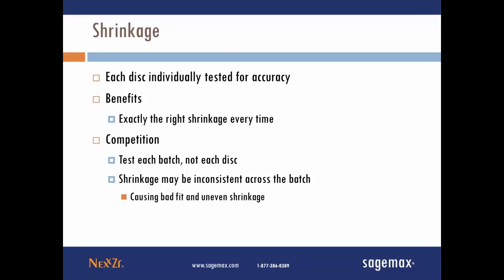And what that would cause is actually a bad fit and possibly even an uneven shrinkage value across the zirconia blank. As you know, in our industry, we need to take marginal integrity and fit for granted. You have to have those two factors in any type of material that you're using. And if your marginal integrity and your fit is not there, the material just doesn't work, obviously.